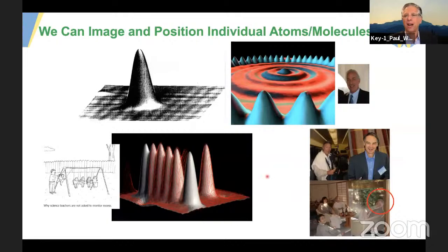Once upon a time, when I was at IBM Almaden, I was the first one to move atoms around. I didn't do that for graffiti or to make these interesting electronic structures, but rather just to find out what was underneath the atoms out in the middle of the terrace. And that made us realize that this microscope wasn't only a structural tool for measurement, but it allowed us to manipulate, and it gave us this idea of precise structures. I'll add that we also learned very quickly about the spectroscopic capabilities. So for instance, in this famous quantum corral, there's no extra atom right in the middle. That's just an electronic structural feature from interference that turns out has important chemical consequences. And we'll talk about that as we go along.